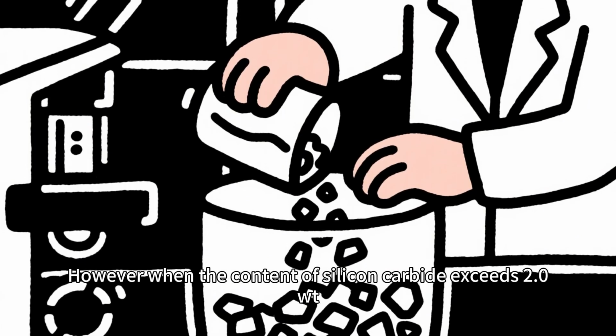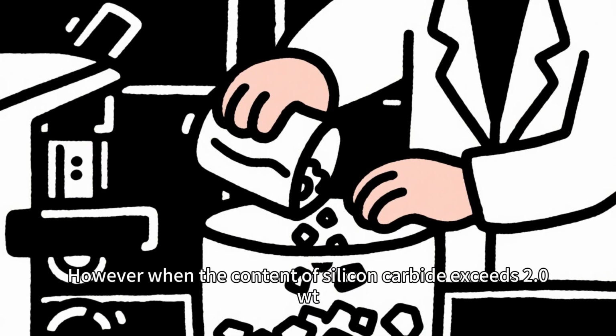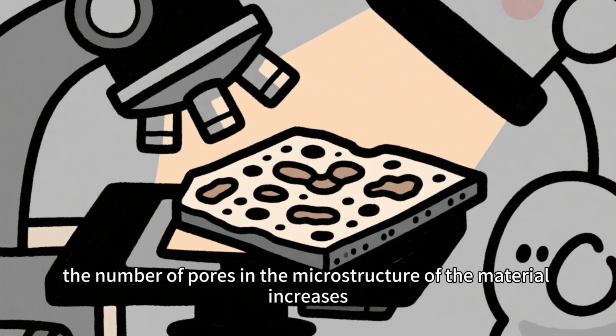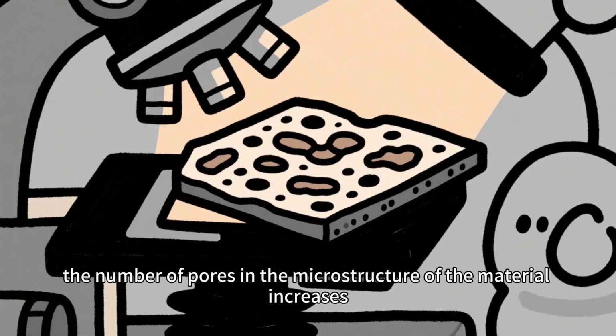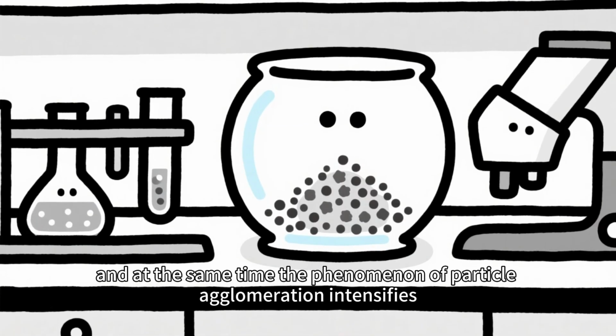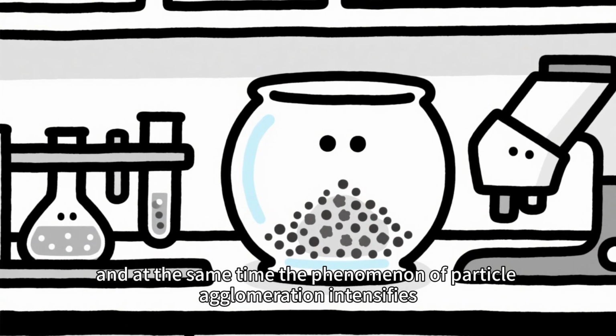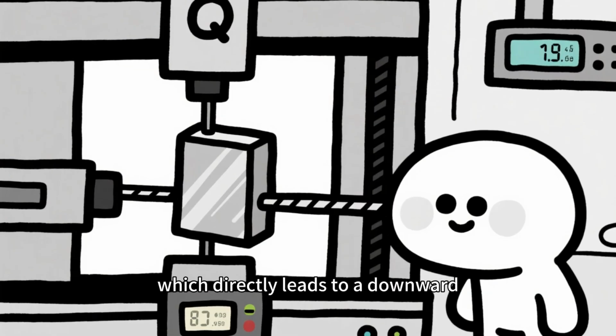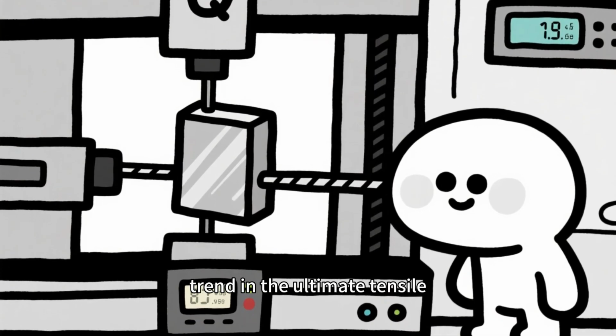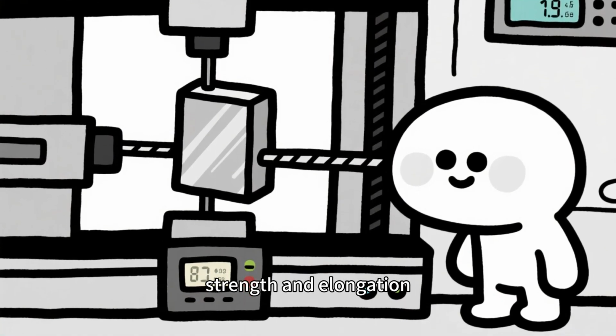However, when the content of silicon carbide exceeds 2.0 wt%, the number of pores in the microstructure of the material increases, and at the same time, the phenomenon of particle agglomeration intensifies, which directly leads to a downward trend in the ultimate tensile strength and elongation.